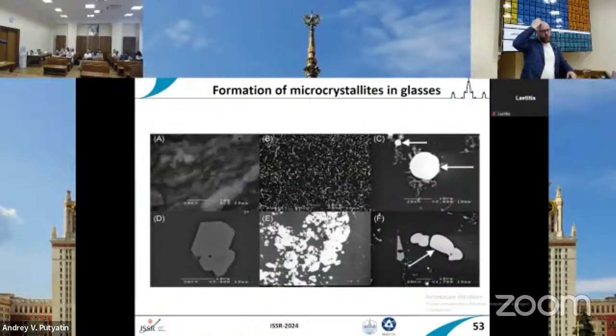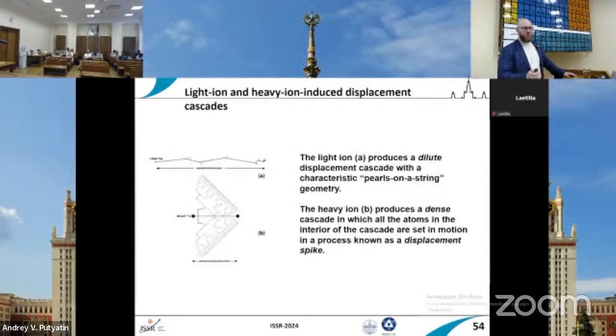Also, what is important due to the storage of glasses and due to the radiation and chemical transformation of glasses is the formation of these dendrites or microcrystallites of solid phases inside the glass. And again, due to the radiation, due to the formation of vacancies in the structure, it becomes easier for elements to diffuse in the glass and to accumulate and form these microcrystallites in glasses. So it's a bad situation for glasses because they become not amorphous but crystalline, and it is not good for glasses.